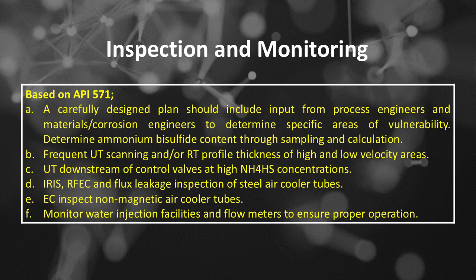Ammonium bisulfide corrosion in alkaline sour water: inspection and monitoring based on API 571. Number A, a carefully designed plan should include input from process engineers and materials/corrosion engineers to determine specific areas of vulnerability. Determine ammonium bisulfide content through sampling and calculation. Number B, frequent UT scanning and/or RT profile thickness of high and low velocity areas. Number C, UT downstream of control valves at high NH4HS concentrations.